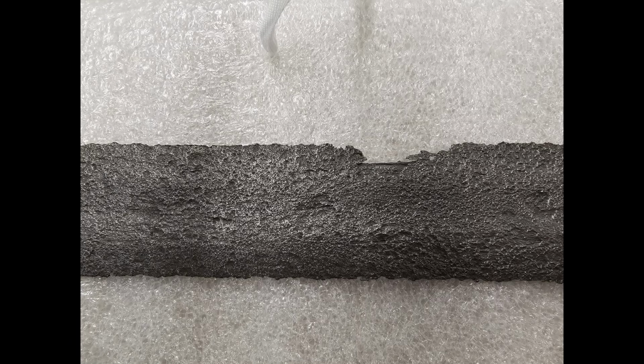The sword was analyzed by means of a handheld XRF tool. This is a non-destructive analysis technique that can determine the chemical composition of the metal alloys in the steel. Unfortunately, the tool also has some limitations. In particular, lighter elements cannot be measured accurately, so carbon content and phosphorus content cannot be judged with the handheld XRF, but the metal alloys can be determined very accurately, even at quite low concentrations.